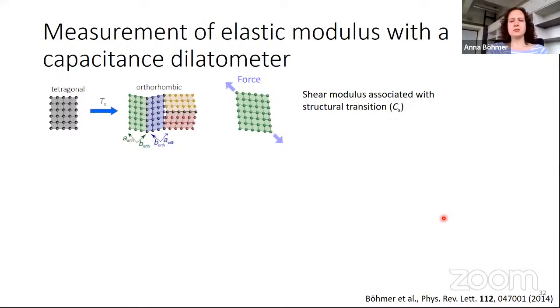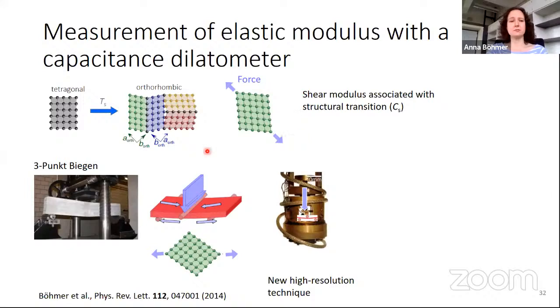What we used, which I think is cool, is a new way to measure an elastic modulus using a capacitance dilatometer. We basically apply a force to our crystal. We go back and forth and we measure how much force we need for dilating the crystal by a certain amount. That's called shear modulus, and the technique is actually old. It's a 3-point bending, and that's been used in engineering forever. When you want to build a bridge, you want to test your material, that's what you do. But we do it in our dilatometer. We apply a little bit of force and we measure the length change, how much this bends, with a fraction of angstrom resolution. So we have a new high resolution technique there.